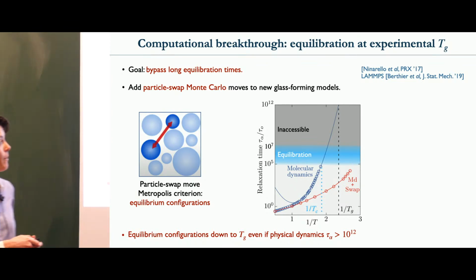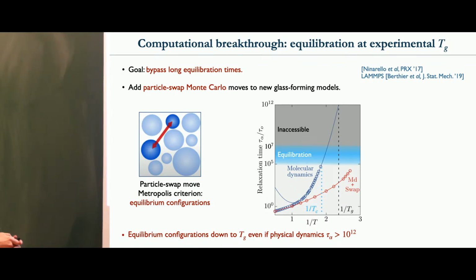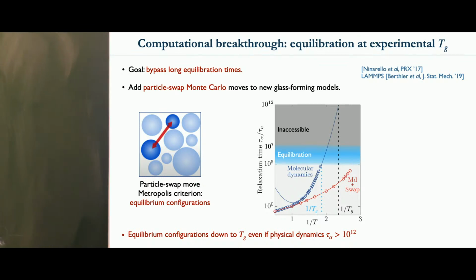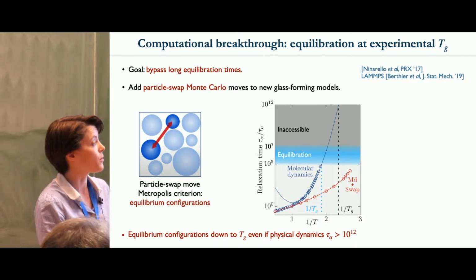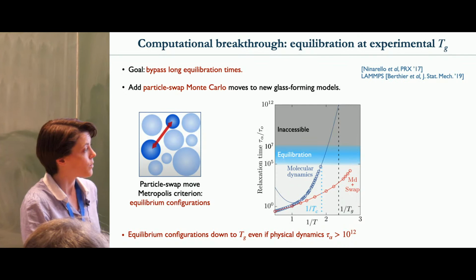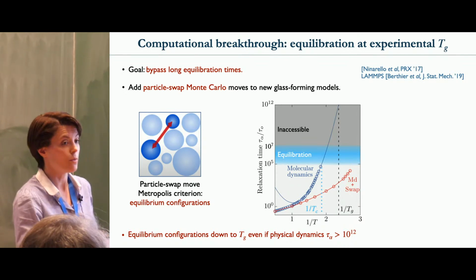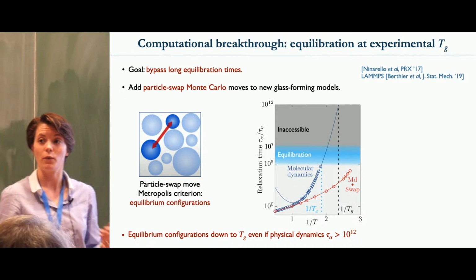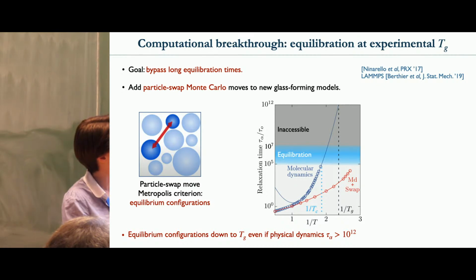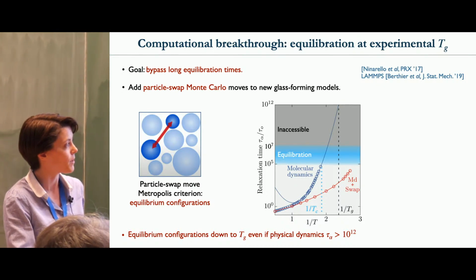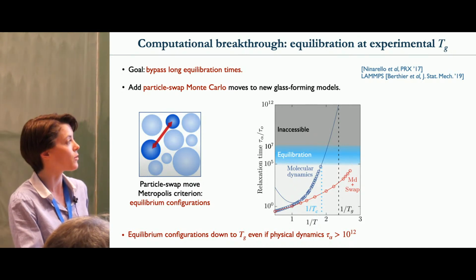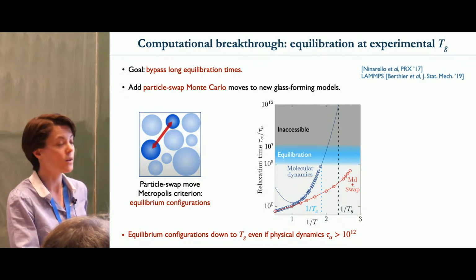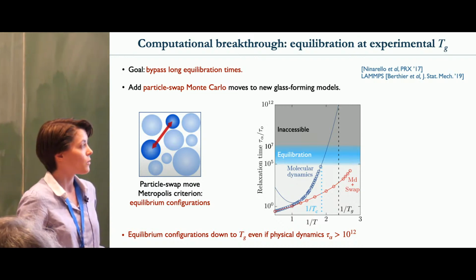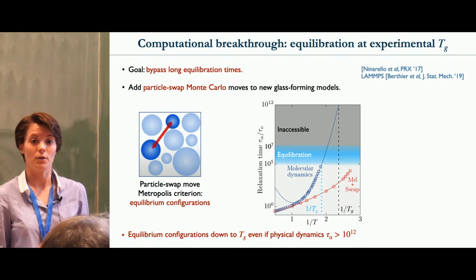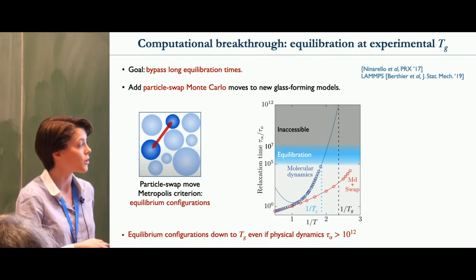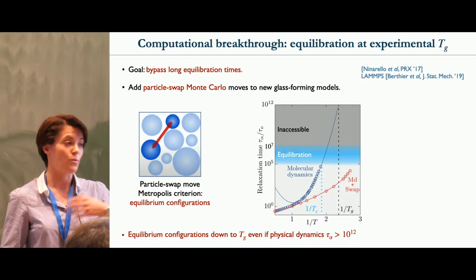So the goal here is really to bypass this long equilibration, which is really limiting the timescales that we can study. So the major consequence of this particle swap algorithm is the following. If you investigate the liquids at a low temperature, so let's say here on the right, you see that the real physical dynamics is actually too long to be able to simulate. But now if you add just a small change, these particle swap moves, what you have is that the dynamics is dramatically sped up, and you can actually, in this swap dynamics, measure the relaxation time, which means that you're still in this region here where you can do equilibrium simulations. So the consequence is that you have access to equilibrium configurations at temperatures that are down to the glass transition and actually even below, even though the physical dynamics is really too slow.